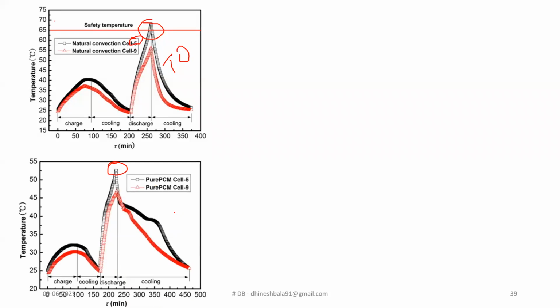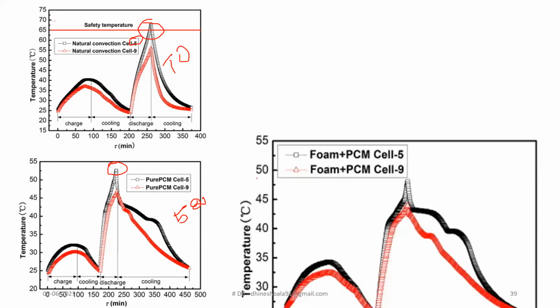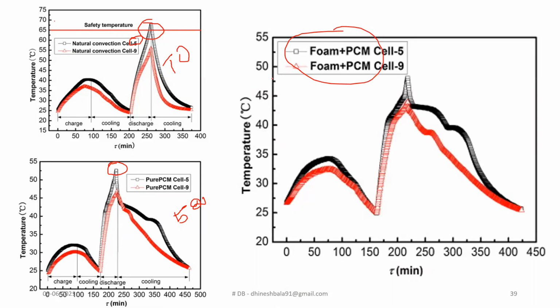For cell number 5, the temperature exceeds the safety limit of the lithium battery operating temperature range. It is close to 70 degrees Celsius. But if you incorporate the PCM, the temperature has fallen to 52 degrees Celsius for the same operating condition. And when you incorporate metallic foam with PCM, the temperature has further reduced to 48 degrees Celsius. So here you can see the temperature transition from 70 degrees Celsius to 48 degrees Celsius, without making use of any external source of energy to thermally control your battery